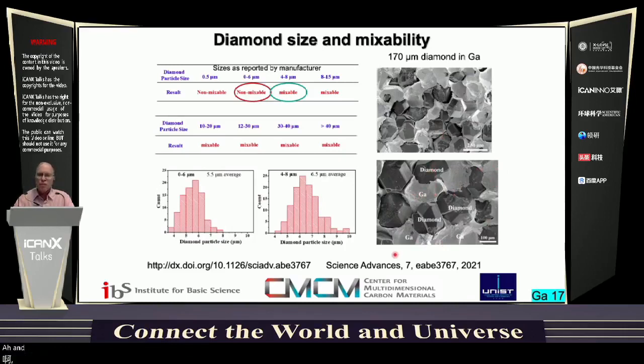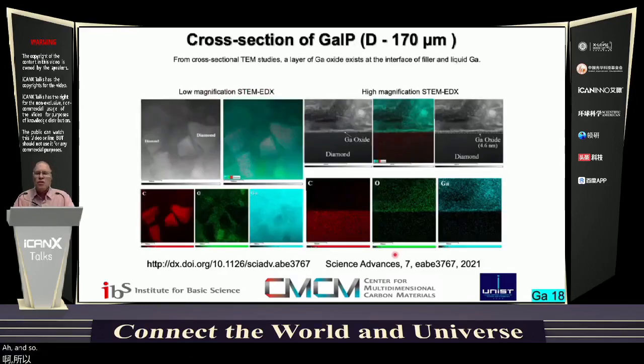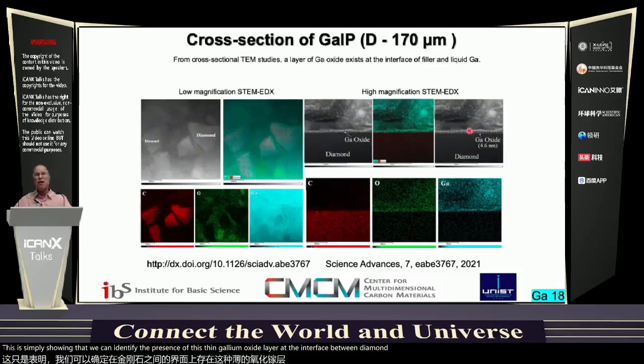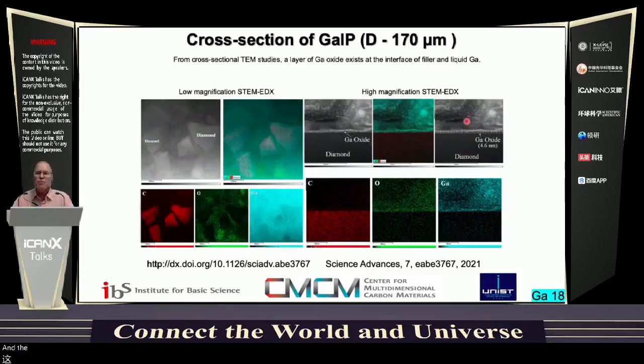And so this is simply showing that we can identify the presence of this thin gallium oxide layer at the interface between diamond and the gallium matrix, for example.